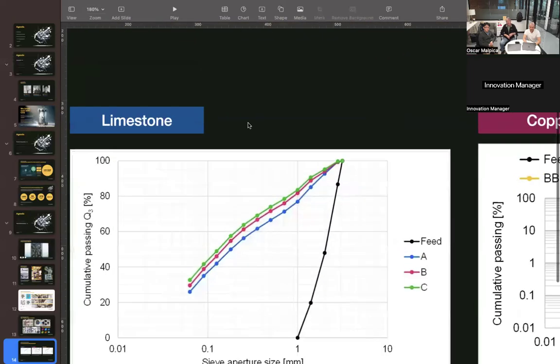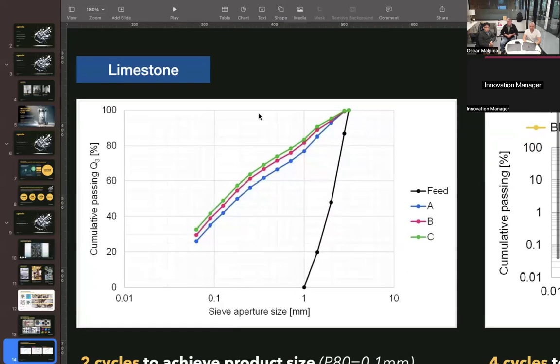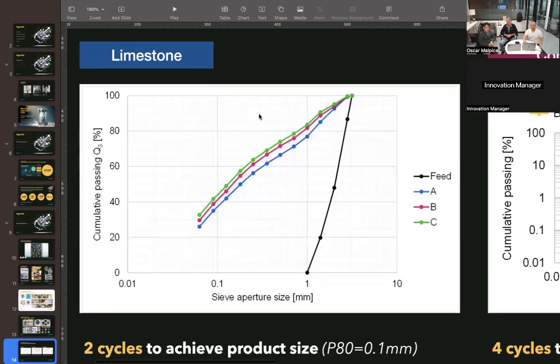This is an example of particle size distribution charts, to back up the pictures of the products that we produce from the feed. These are intended to show our breakage performance. These are showing individual cycles. So each chart has a black line which shows the feed size, and these sizes are all produced by taking first the feed, the black line, and then the products, the colored lines from the tests, and putting them in sieving machines and sieving them at different sieve sizes so that the mass of the particles that pass through a certain sieve size can be determined and then charted here.